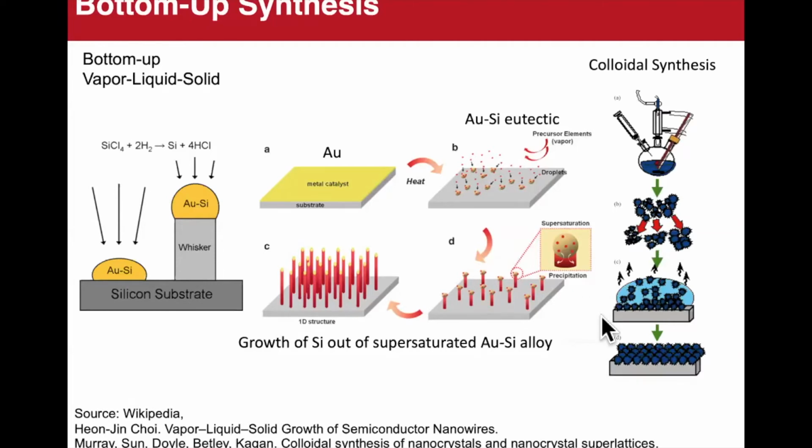Christopher Murray, as a graduate student in the 1990s, demonstrated controlled synthesis of quantum dots, which can then be self-assembled into a variety of substrates. Here you can see that this is solution phase synthesis, in which injection of precursors occurs and temperature is monitored. From the formed nanoparticles, the solvent can be evaporated, and these self-assembled nanoparticles can be deposited on a wide variety of substrates. So this solution processing technique enables deposition onto flexible substrates and any other substrate that you can think of.